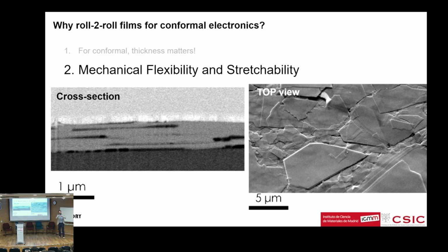You can imagine that if you apply a mechanical deformation to these films, these flakes are going to slide against each other. Importantly, as I said in the introduction, van der Waals materials don't have dangling bonds on the surface. Therefore, they have this good sliding because they don't get stuck. So we believe these roll-to-roll films are going to be good for fabricating sensors that can integrate on rough surfaces as a second skin.